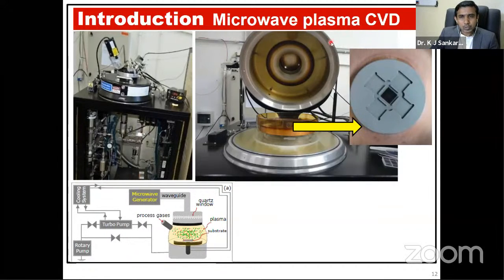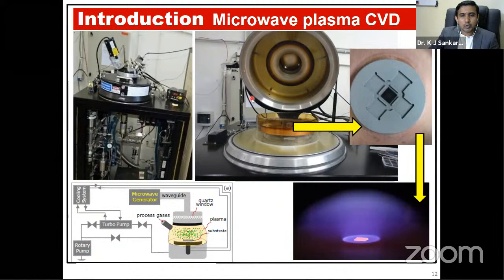Once you close this chamber, we create vacuum, and then we start growing the diamond films by passing gases. We can use different gases for different applications of diamond, and then we use the microwave. Once the microwave passes through the chamber at a particular pressure and temperature, you can see a very uniform plasma that forms over the substrate holder. This is the plasma formed on the substrate holder, which has the silicon substrate here. Depending on the process gases that we are using in the growth, we can achieve different colors of plasma.